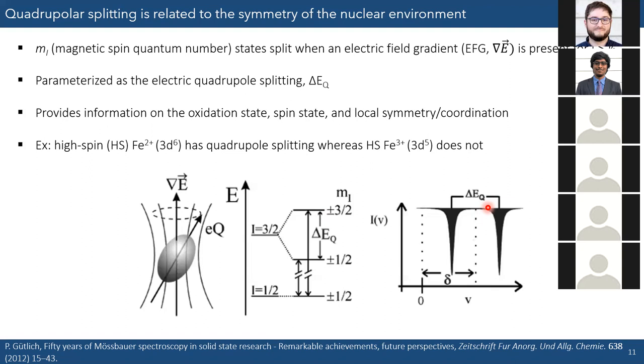And so a nice example of this is if you're looking at high spin iron 2+, which has an electron core configuration of 3d6, versus high spin iron 3+, which is just 3d5. So all of the d orbitals for iron 3+ are going to be very equally occupied by electrons because there's 5 orbitals. And so that's going to have a very symmetric environment. Whereas for iron 2+, it's going to have an extra electron in an orbital.